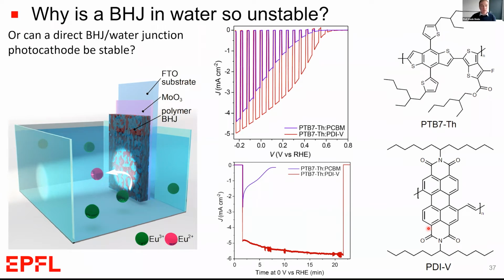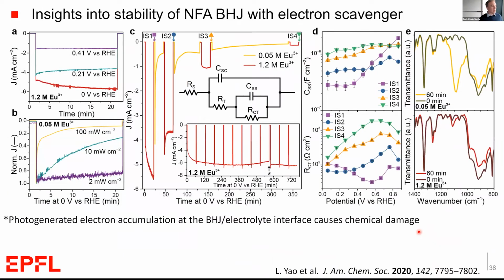But nevertheless, we still wanted to test this system to see how stable it could be. We performed a lot of different tests at different light intensities, at different potentials, and using analysis techniques like electrochemical impedance spectroscopy and FTIR. And I don't have time to go into this, but the main conclusion is that we can still see a lack of stability in these systems if photo-generated electrons are accumulating at that bulk heterojunction electrolyte interface. That causes chemical damage if we accumulate too many charges.